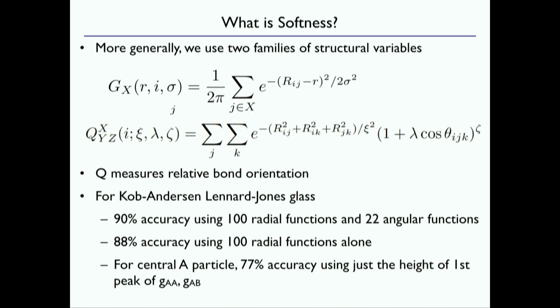And just using the height of the first peak of this pair correlation function. If I look at these pair correlation functions averaged over all the particles, there's a nice first peak. And I look at the local g(r). For each particle, I can pick out the value of g(r) at the value of r where the peak is for the average g(r). For g_AA and g_AB, just using those two numbers, you can get 77% prediction accuracy. It's actually not terrible.